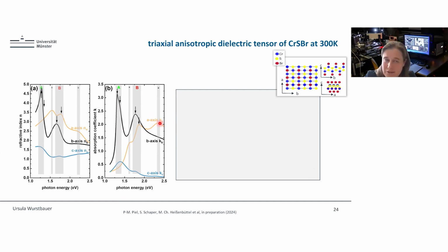I guess I just got confused by A and B. Sorry again. So the black trace is the B-axis, which dominates the low energetic part. In the intermediate range, both of them contribute, and in the higher energetic part, the A-axis contributes more. In the out-of-plane direction, we have some contributions, but they are not that significant, and it could be that we still have a mixture due to some surface roughness, which is difficult to separate in this kind of experiment.